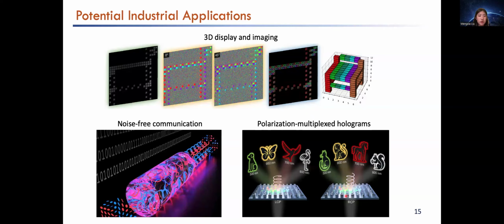This means that when using polarized, circularly or linearly polarized light to shine onto a hologram, we can generate different patterns. This allows us to store or project multiple holographic images using the same aperture by assigning each image to a very different polarization state. So this can be important for anti-counterfeiting or near eye display.